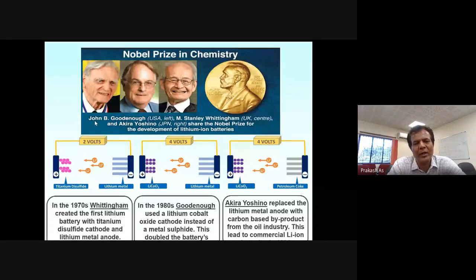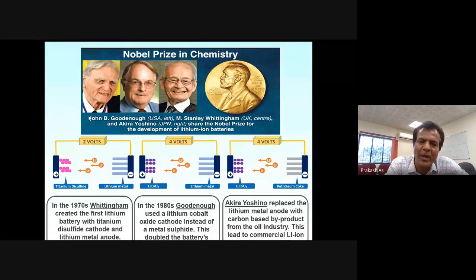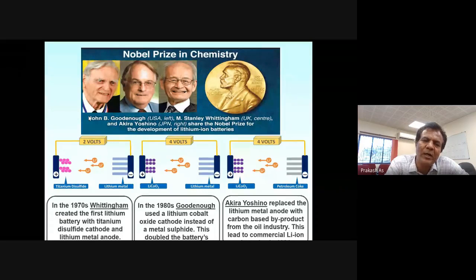Then for a certain time, people were using lithium metal with polymer electrolytes. They were using lithium polymer batteries, with lithium metal, polymer electrolytes, and lithium cobalt oxide and things like that. So those batteries were being used. But one of the issues was that lithium metal is highly unsafe. Lithium is an alkali metal. If it comes in contact with water or air, there could be explosion issues. So it's not safe.